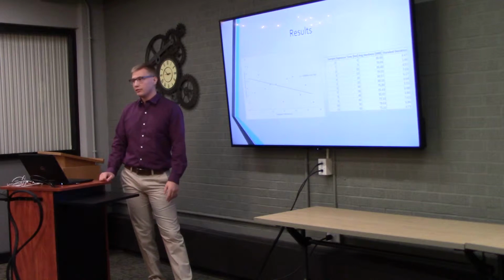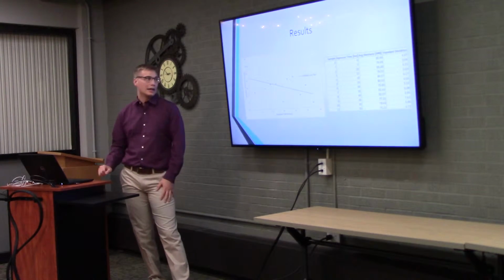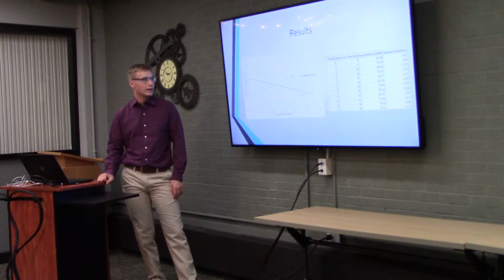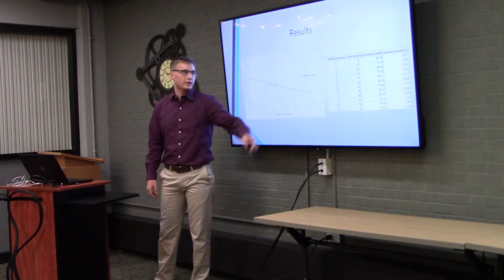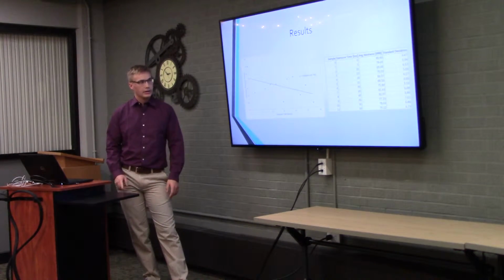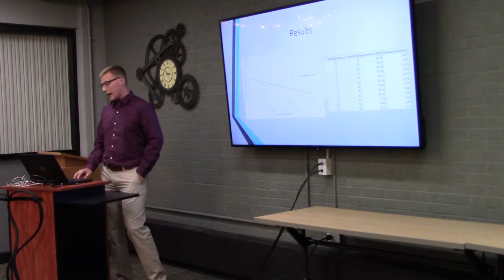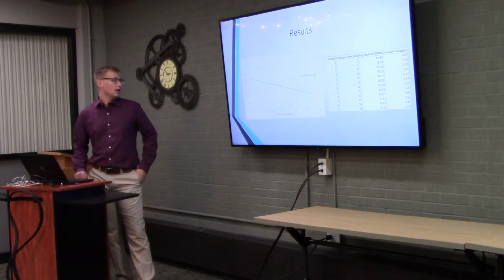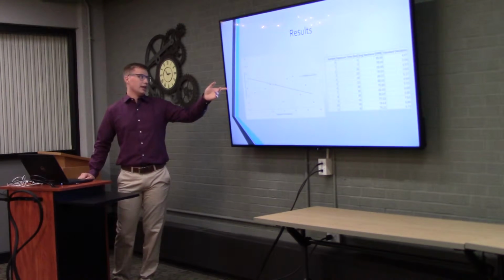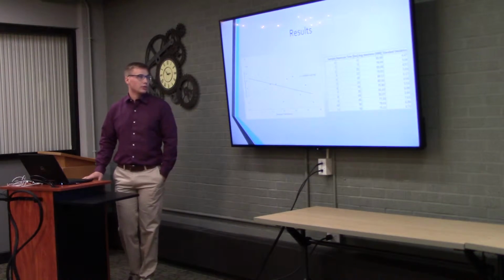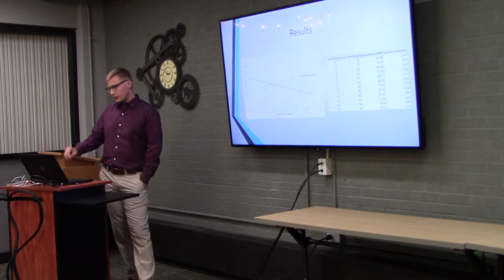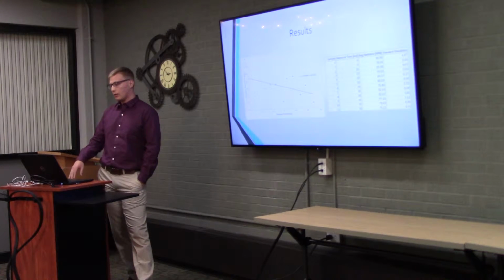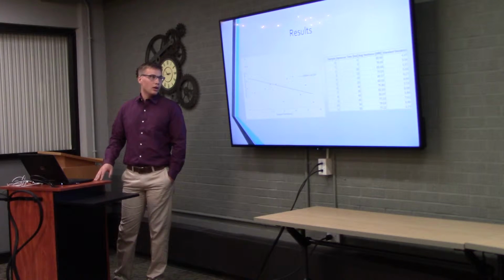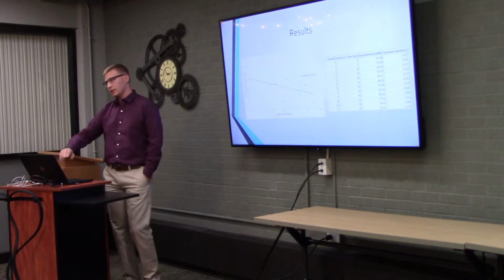So to investigate more, I did do a statistical analysis, which is shown in the next slide. You can also see that the standard deviation over there, all the way on the right, is pretty high, especially when you consider that we're getting values around 80 on the Rockwell hardness scale. So those standard deviations cause concern into how accurate the hardness readings are, because those standard deviations are based on the averages of each sample.